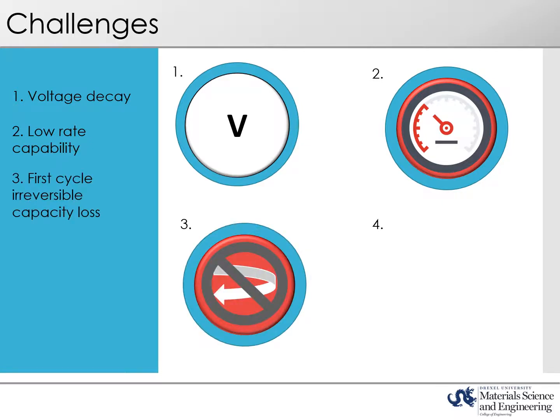First cycle irreversible capacity loss, which is also referred to as low first cycle Coulombic efficiency, where values are less than 80%. The first discharge cycle has a large IRC. During the first cycle, not all of the Li ions extracted during the first charge can be inserted back into the structure, causing the high IRC. These excess Li ions are then free to react with the products of the electrolyte decomposition to form a thicker SEI layer.